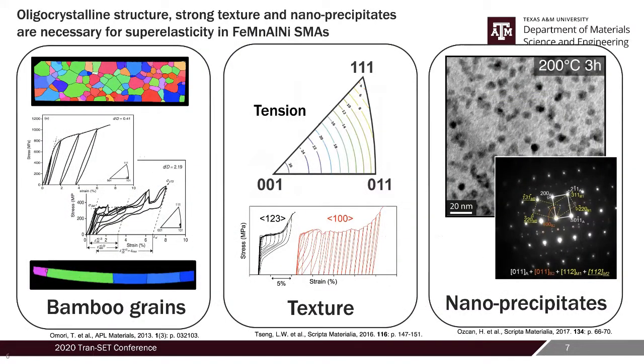However, to get a superelastic response from an iron-based SMA, you need three things. The first thing, which is extremely important, is the grain size. In this graph on the top, what you see is a microstructure of a material, and these little areas we call grains. What you want to do is increase the grain size of the material through heat treatments, abnormal grain growth heat treatments. If you have a small grain size alloy, you don't get that superelastic response that I showed you earlier, which is typical to SMAs. However, if you increase the grain size of an alloy such that the grain size is higher than the smallest dimension of the component, this is important. You want your grain size to be higher than the smallest dimension of the component. It can be bars or wires.